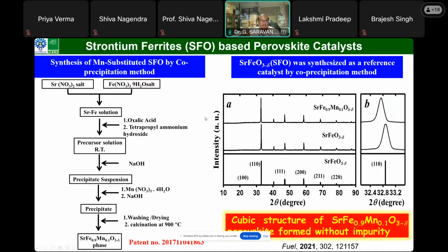So synthesis is quite simple. We can take the appropriate salt, whatever you are targeting, take the stoichiometric amount, add some shape controlling agents and precipitate, followed by calcination at the target temperature. You will get the target phase.